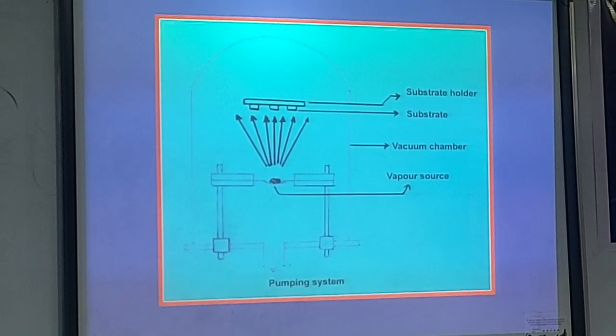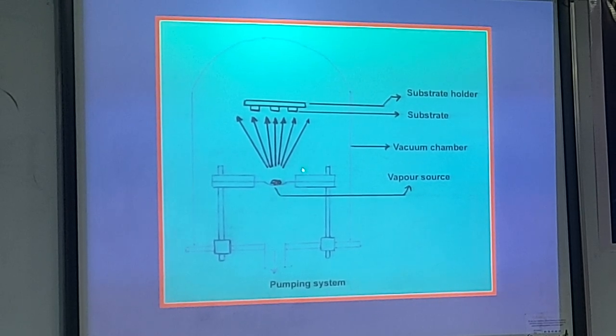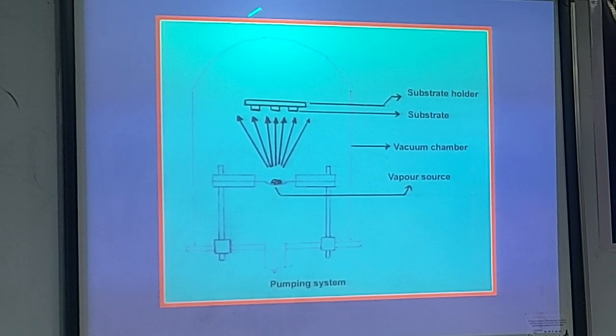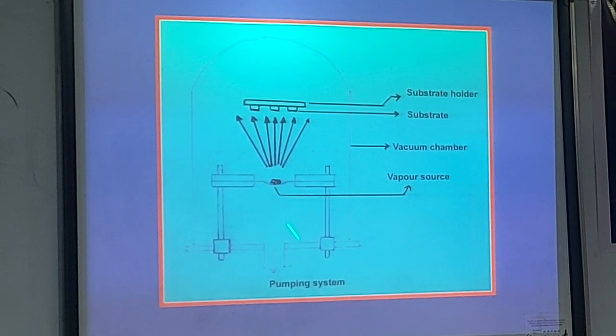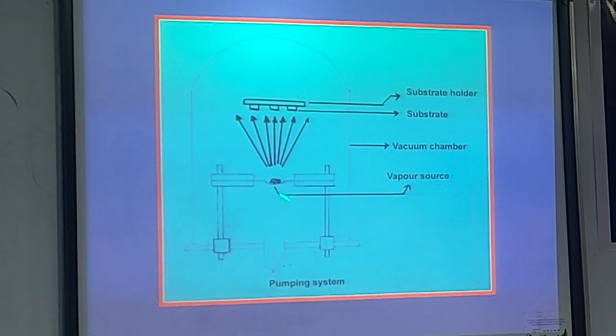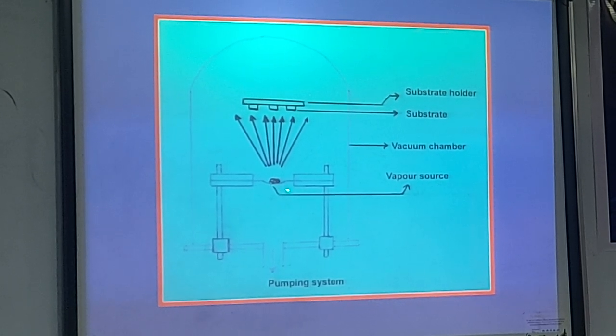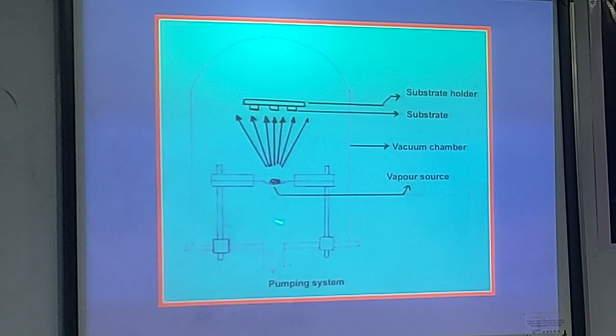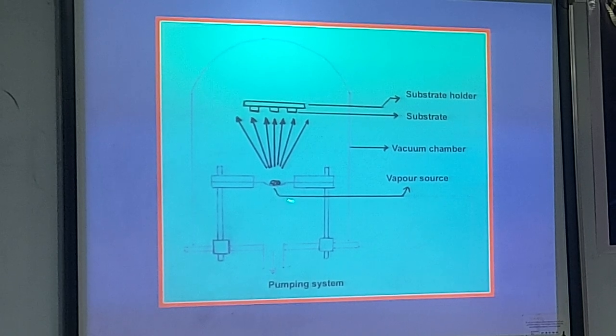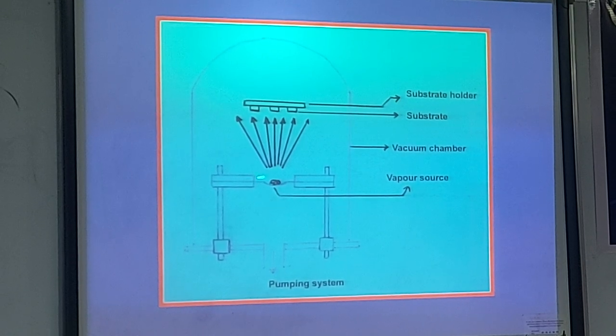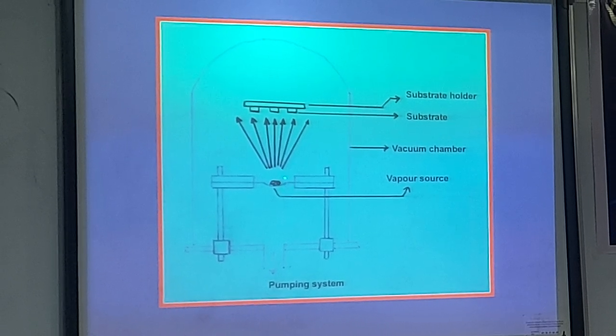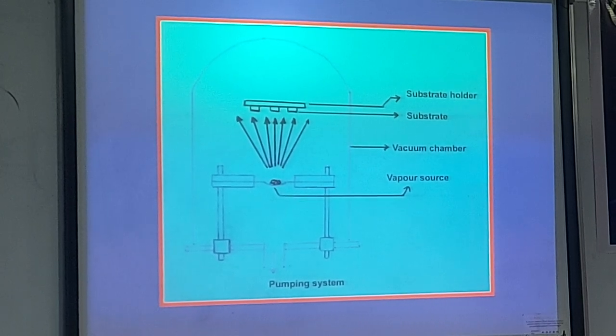So this is the simplest evaporation technique. What we do is, we take the material to be deposited in the form of a filament or a boat, and this is a vacuum chamber. We remove the gas, create a vacuum as low as about 10 to the power minus 5 torr or minus 6 torr. We heat the material. The material melts, comes to the vapor state, and now it gets coated on the substrate. This is the simplest technique to prepare a thin film, vacuum evaporation. Since we are heating by passing electric current through the source material, either a filament or a boat, it is called the resistive heating method. So this is the simplest method, but it has its own limitations.